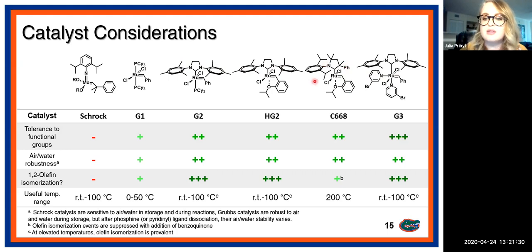One thing I want to point out, which is a recent development, is this catalyst, we call it C668. That's what it says on the bottle. It's kind of a unique metathesis catalyst. The unique thing about this is that it can do metathesis reactions up to 200 degrees Celsius, which up until very recently was impossible without either catalyst degradation or a lot of olefin isomerization. In this case, you can add a little bit of benzoquinone to the reaction, which suppresses the formation of ruthenium hydride, and you can get really nicely precise polymers that are made at really elevated temperatures.